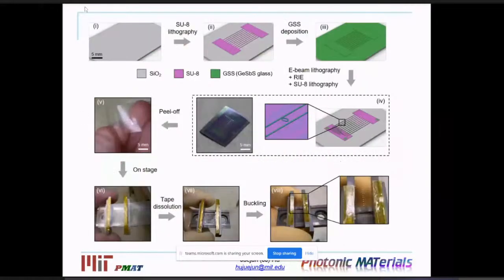So that's why we have proposed this technique to create a three-dimensional structure and then embed it in a three-dimensional tissue model. What I'm showing you here is the fabrication process in more detail. We started out with a lithographic definition of these bridge patterns. We then create different kinds of photonic devices on the photonic bridges. In particular, we created resonators so that by looking at the resonance shift, we can monitor the local strain and stress in the three-dimensional tissue.